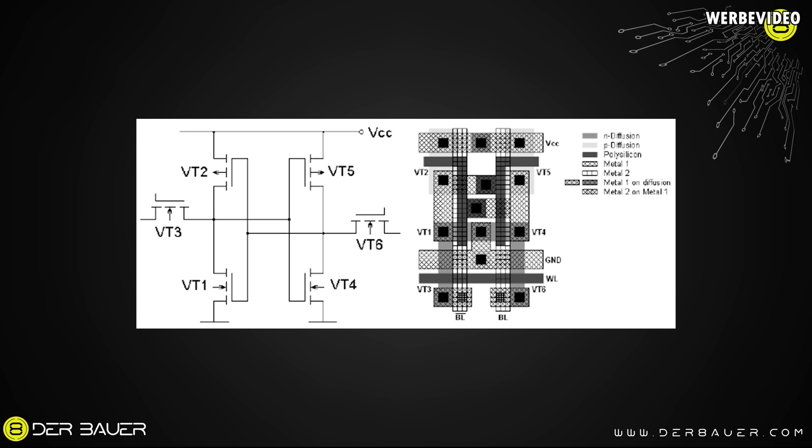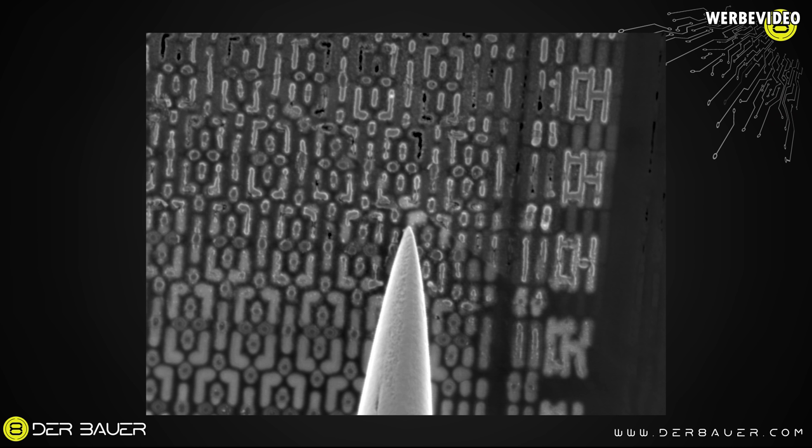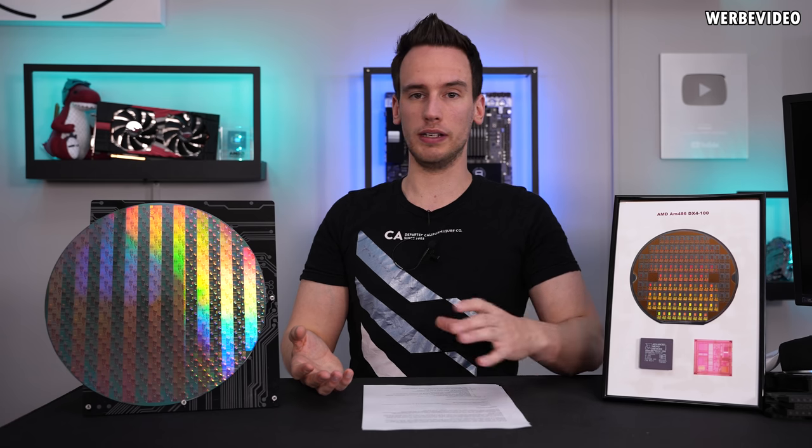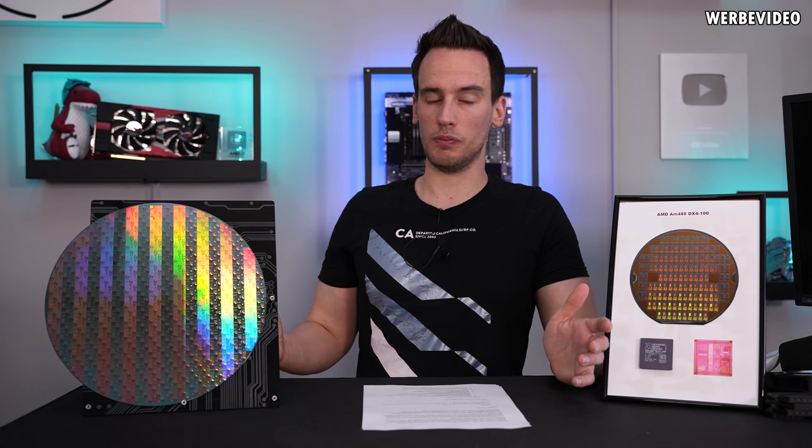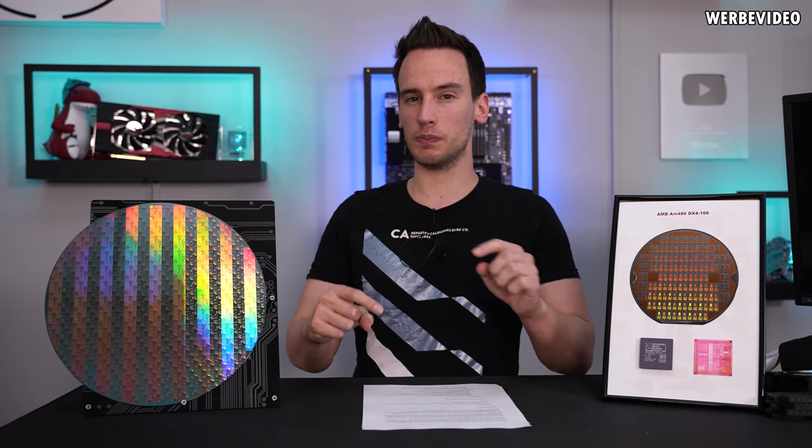Now, the big issue with those SRAM cells is that, for example, with TSMC 7-nanometer, they're using cobalt. And cobalt easily forms an oxide layer once it's exposed to the ambient air. So if you're preparing those chips, grinding down, etching, whatever, and you leave it in the ambient room for, I don't know, like a day, it will easily form a cobalt oxide layer. And this is insulating. That way you're not making contact with the needles anymore, which makes probing of SRAM cells really difficult.